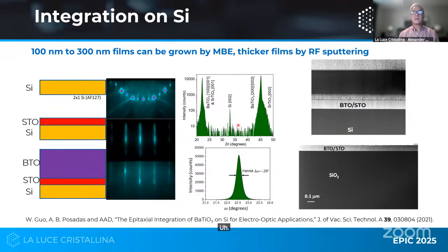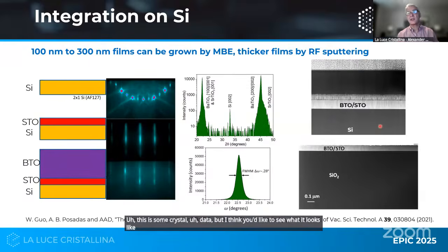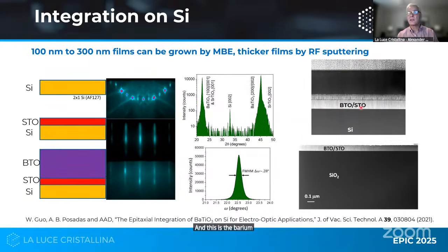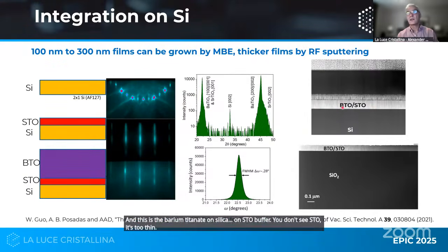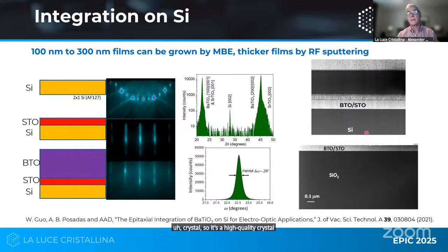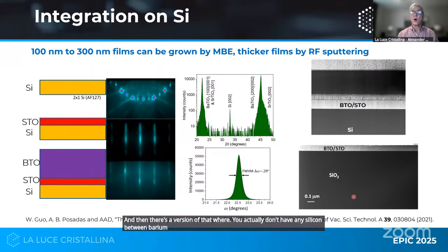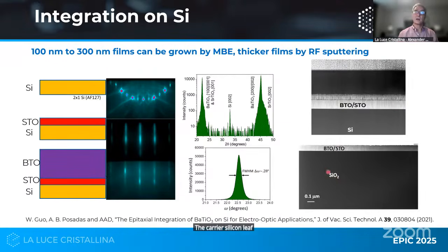This is some crystal data, but I think you'd like to see what it looks like. So this is silicon. This is a silicon substrate. And this is the barium titanate on STO buffer. You don't see the STO; it's too thin. So it's a high quality crystal grown on silicon. And then there's a version of that where you actually don't have any silicon between barium titanate and the box of an SOI wafer. The carrier silicon wafer is below, out of the field of view. So these are thin films.